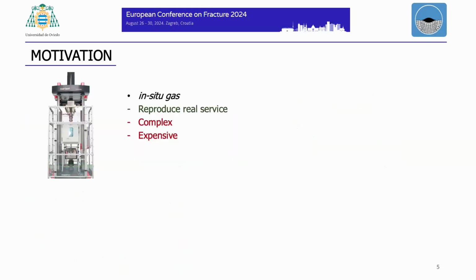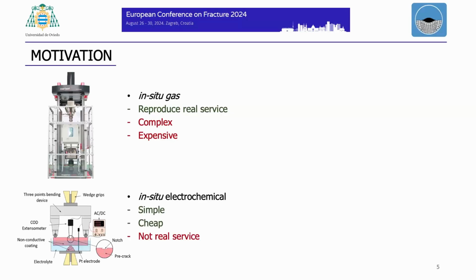To do so, the ideal procedure is to perform tests under in situ gas conditions. It reproduces a real service condition. You can select the pressure you want, but the equipment is quite complex and expensive. So to reduce cost, an alternative is to perform the test under in situ electrochemical conditions. It's simple, it's cheap, but it doesn't reproduce the real service condition. You have to find the parameters that reproduce that condition.